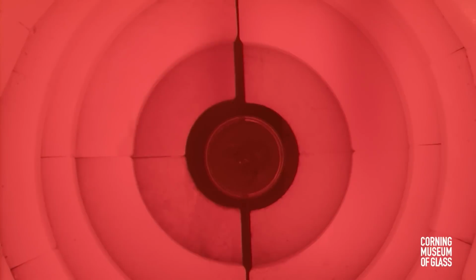And you notice that as soon as we break free from the one pipe or one punty to another, the first thing the person that gets the glass does is goes right up to the heat, right? Because that's a critical moment. And if you wait too long, the temperature drops, and that's when the stem can crack, the foot can crack. So you got to get right back up to the heat. Waste no time.